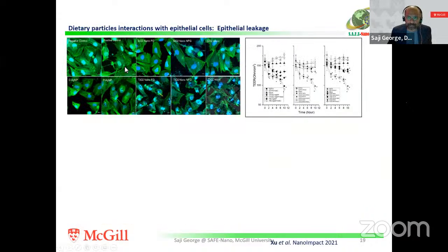And in fact, we found that with nanoparticles, again, not with micron particles, we can see these tightly bound or adhering cells now get separated, where in the presence of nanoparticles, you can see in confocal microscopy the gaps between the cells opening up, as in the case of titanium dioxide, or with a positive control here, or with even silver nanoparticle, we can see the same kind of effect. We can also quantify that by measuring the electrical resistance across that epithelial layer, and you can see as a function of concentrations of these nanoparticles, especially with the silver, or with a higher concentration of silica, or with a higher concentration of titanium dioxide, there is a drop in the resistance, which is also an indication that there is an opening up of the gap between the cells.